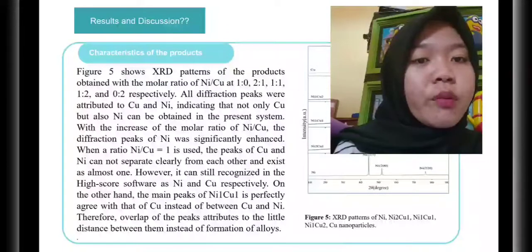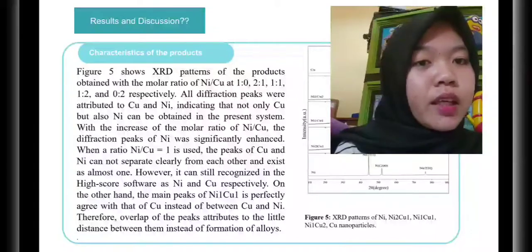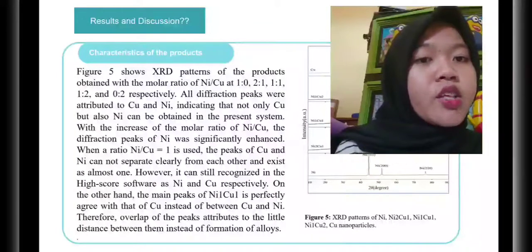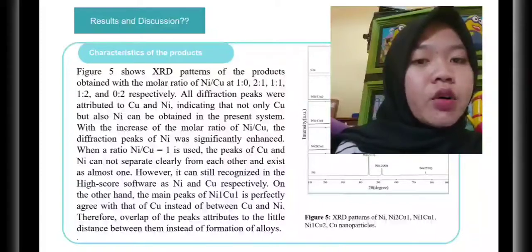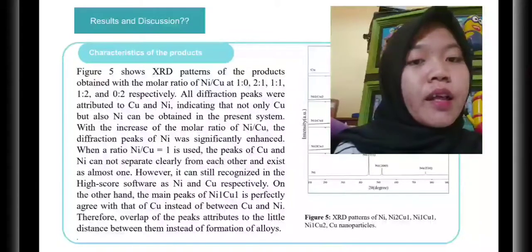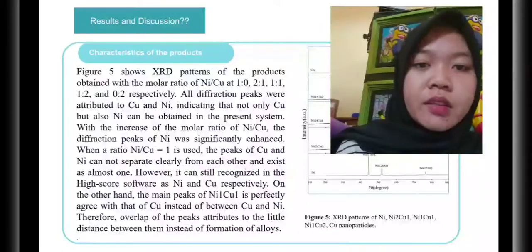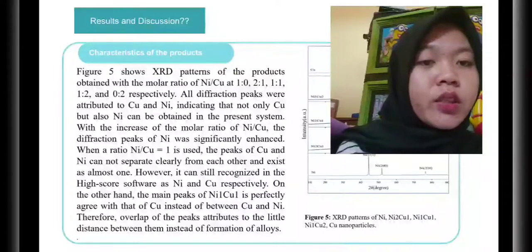With the increase of the molar ratio of nickel to copper, the diffraction peak of nickel was significantly enhanced. When a ratio of nickel to copper of 1 is used, the peaks of copper and nickel cannot be separated clearly from each other and exist as almost one. However, they can still be recorded using the High Score software as nickel and copper respectively. On the other hand, the main peak of nickel 1, copper 1 practically agrees with that of copper instead of lying between copper and nickel. The overlap of the peaks is attributed to the small distance between them instead of the formation of an alloy.